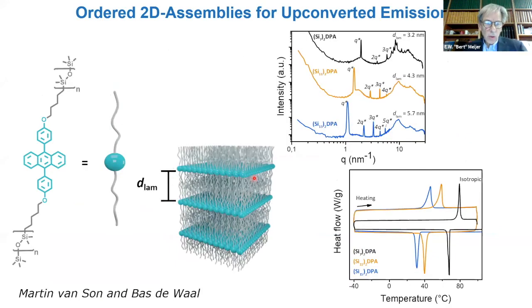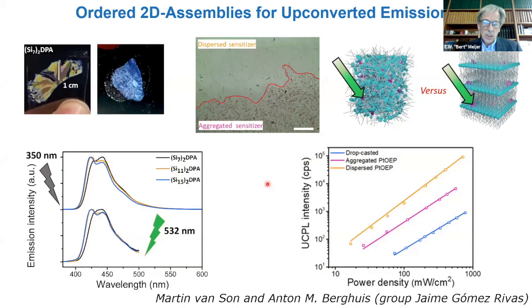Very recently, Martin van Son synthesized one with diphenylanthracene. And with this discrete siloxane, again, you make lamellar 2D structures that are perfectly aligned. And we thought this would be great to use for triplet-triplet annihilation experiments in which you add a sensitizer at 0.1%, you irradiate this, the excitation goes to the acceptor, which is then the diphenylanthracene, and two triplets go to a higher-lying energy state, and the luminescence comes out. This is a technique used by many, many people. Well, we like to do that in a polymer material and more or less as a single crystal.